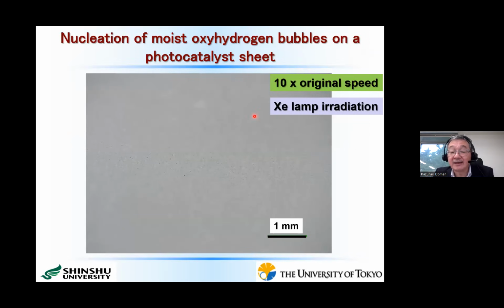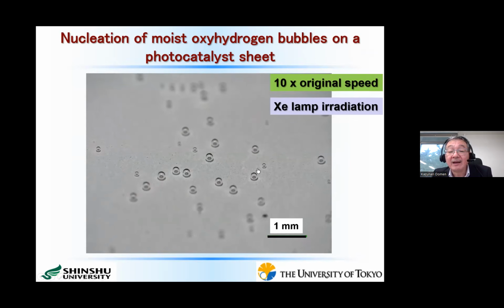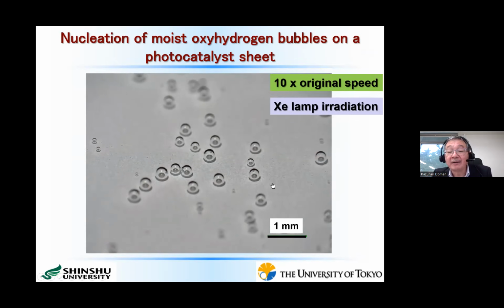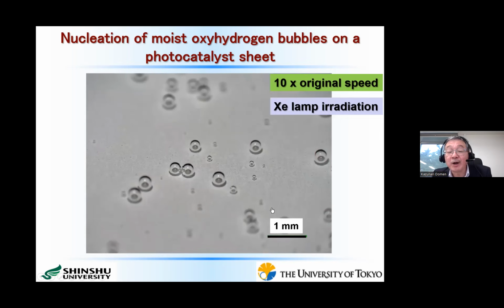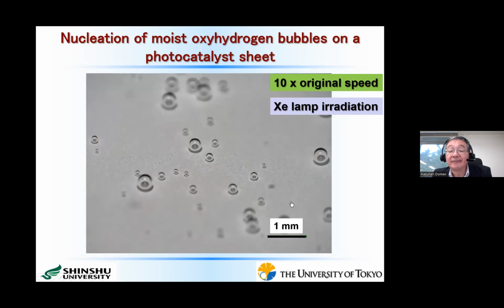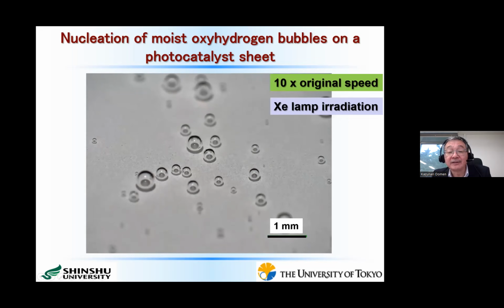Here I show just optical microscopy images, and this is 1 millimeter in size. So you see that we have a very small number of bubble formation sites, about 4 sites per 1 square millimeter, like this one. Okay, this is a real situation of forming the bubbles of hydrogen and oxygen.